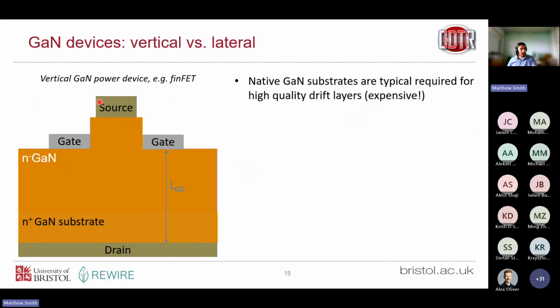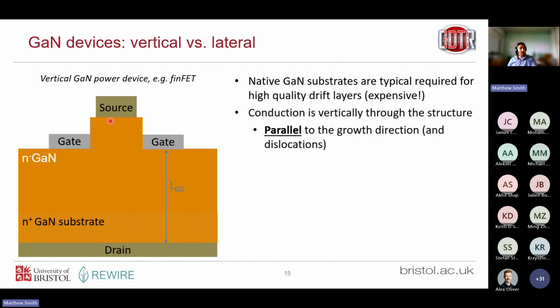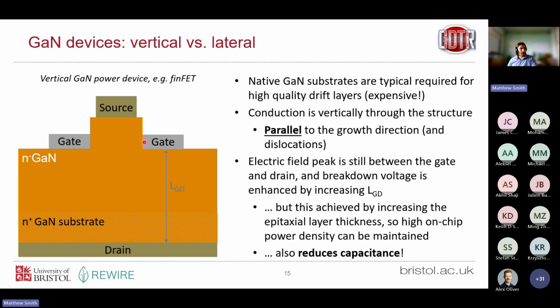So contrast that with vertical GaN devices, where now we've got a gallium nitride substrate, which is very expensive, but it means we now have much higher quality gallium nitride epitaxial material. So our dislocation density is much less. And this time we're conducting vertically through the structure, parallel to our dislocations, but we've got a lot fewer dislocations because we're on gallium nitride substrates. The electric field peak is still between our gate and drain, so it's still this distance here.